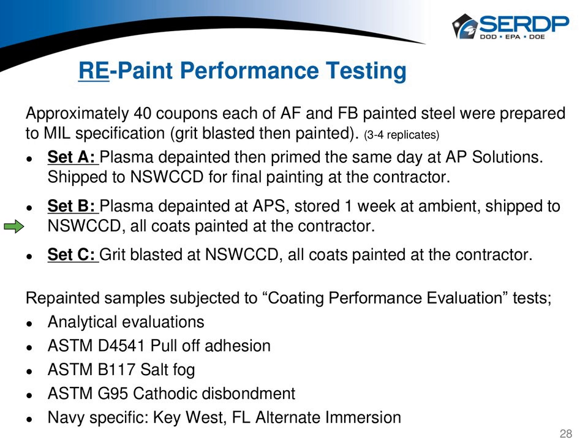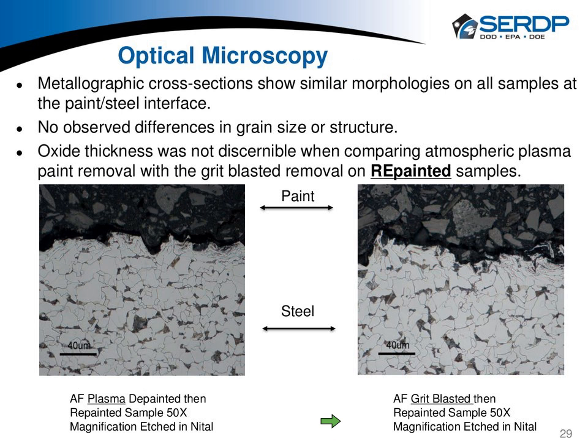Then we shipped them to the contractor where they sat for at least another week before the first set of primer was even put onto the surface. And then the final set was the control set of grit blasting. All of these samples were subjected to lots of different kinds of testing, environmental and analytical. So the first result I'm showing here was the first thing we wanted to see.